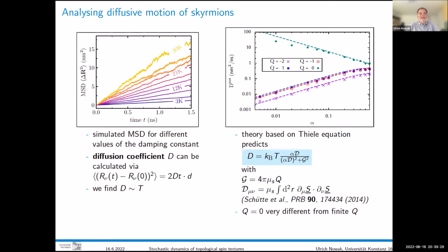So the authors in that study called that suppression of diffusion. Because Q equals 0 has a very high diffusion coefficient. And if there is something topological, a finite topological charge, then you get orders of magnitude lower diffusion coefficients, because low alpha, that's what is realistic experimentally here somewhere. So they call that suppression of diffusion by the topological charge.